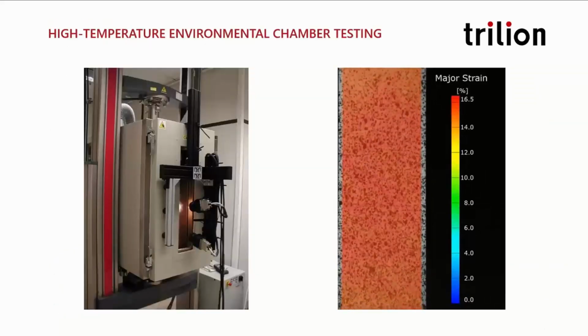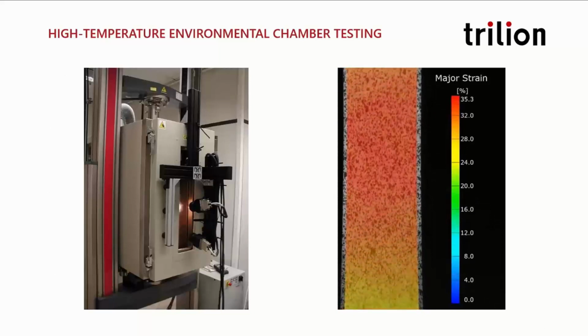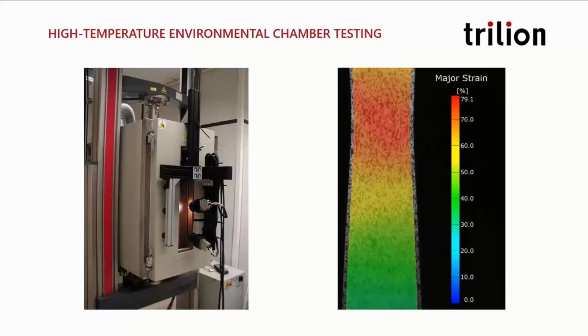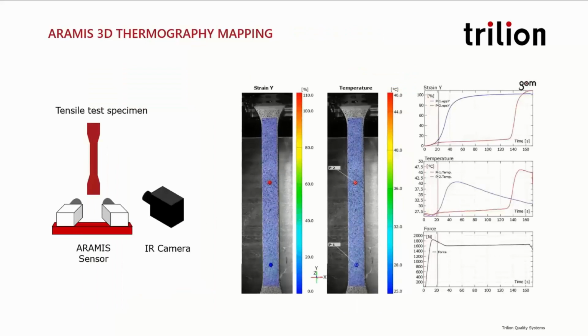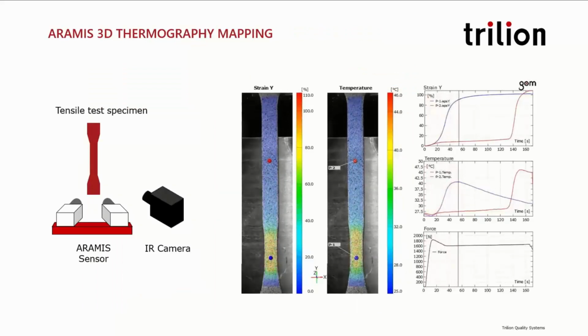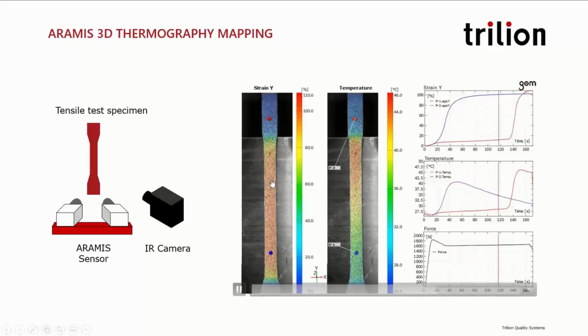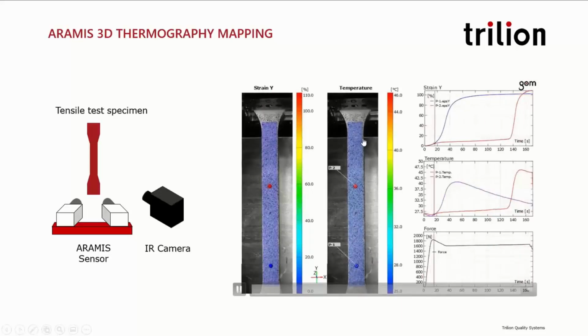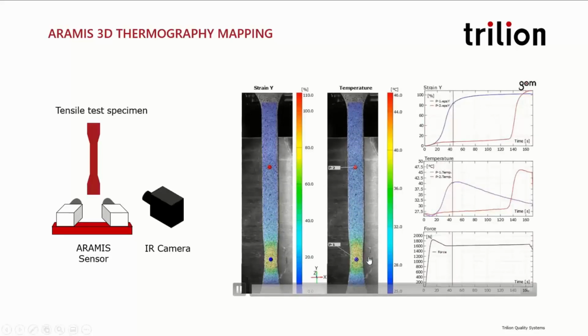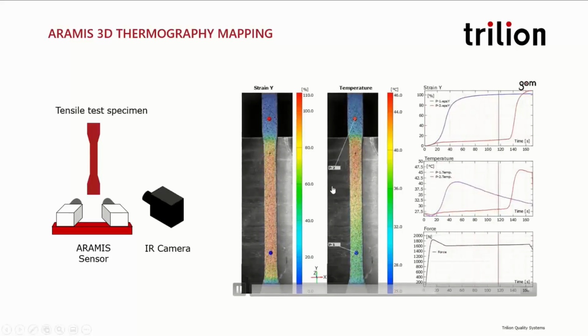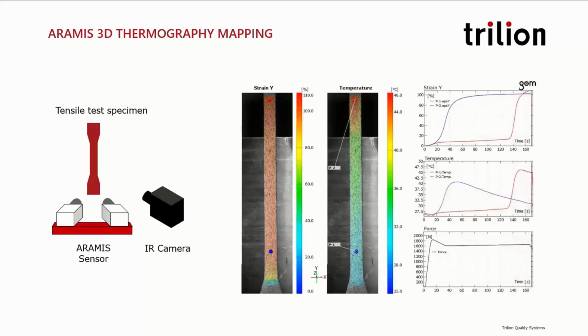We've now applied this to being able to look at materials in an oven, as an example, looking through windows. Here's an ARAMIS thermography measurement where the strain is on one side, and this is what's happening or going to happen, where the temperature is showing you where the stress is actually happening. And so you can see the temperature flow and the strain together really tell the whole story of what's going on with this material and structure.